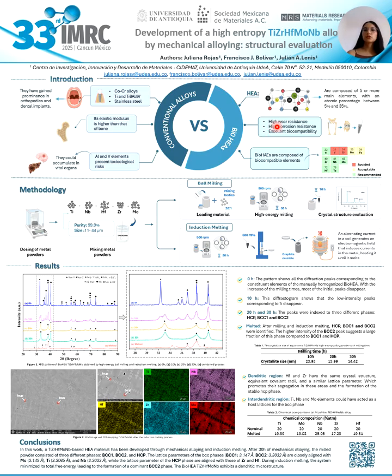These materials are composed of 5 or more main elements with an atomic percentage between 5% and 35%. High entropy alloys in the biomedical materials field, called bio high entropy alloys, are mainly composed of elements commonly found in biocompatible binary and ternary alloys such as titanium, zirconium, hafnium, molybdenum, tantalum, niobium, among others. Research on bio high entropy alloys has grown quickly due to their high wear resistance, high corrosion resistance, and excellent biocompatibility, making them promising candidates for hip prostheses, artificial joints, and dental implants. Therefore, they could be a solution for the problems that conventional alloys can't address.